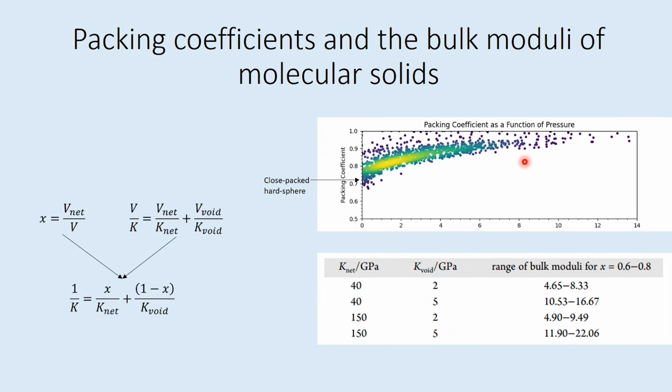Yeah, so the first thing I'd like to point out is this is a heat map. There is actually a very high density of points in this range, so the outliers are quite rare. Looking back at them though, there is no clear, obvious reason why, and I think, to be honest, it's more to do with our use of van der Waals radii not fitting those particular compounds very well. Some that I've noticed especially are ionic compounds.